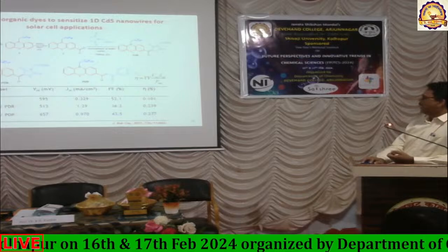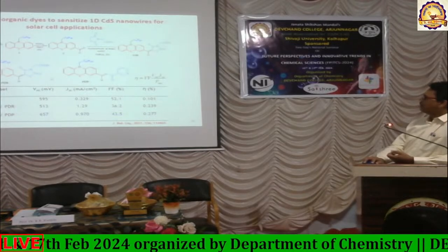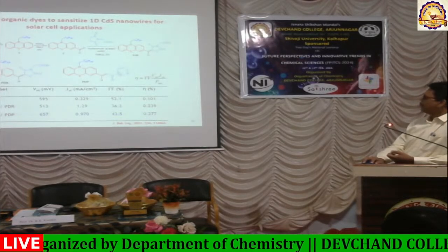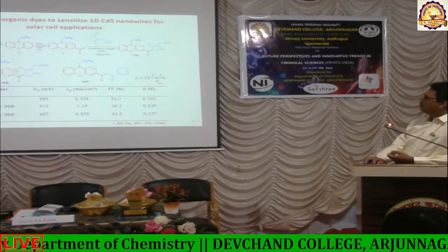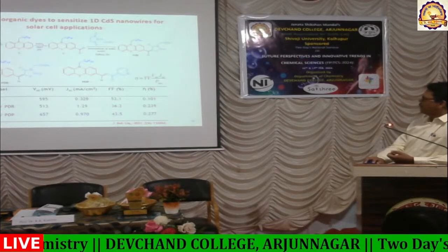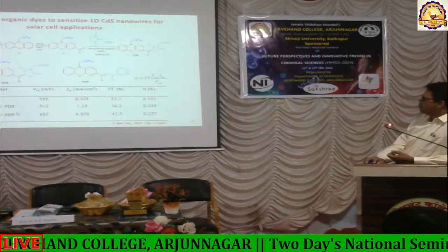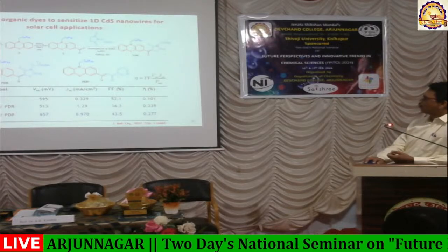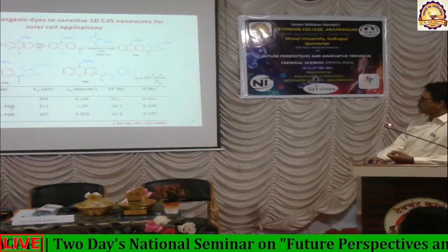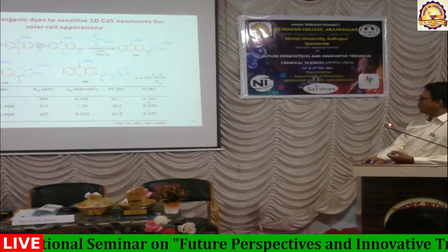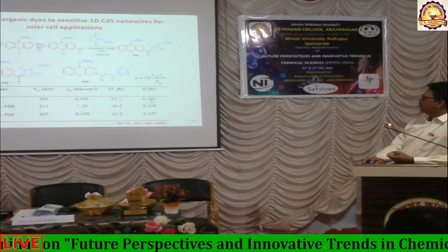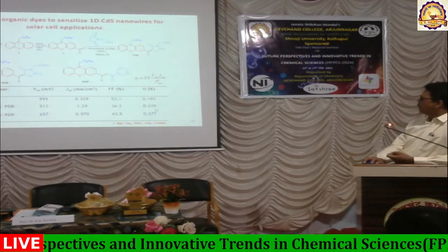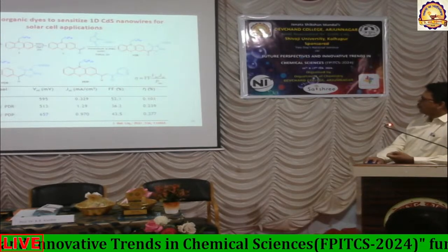This is a linker, and this is a rhodanine-3-acetic acid, and this is a pyridine as a linker we used on the phenothiazine dye. We could see that with this PDA, where the linker is a rhodamine, we got CdS nanowires also exhibiting the sensitization property, but the efficiency was 0.1.